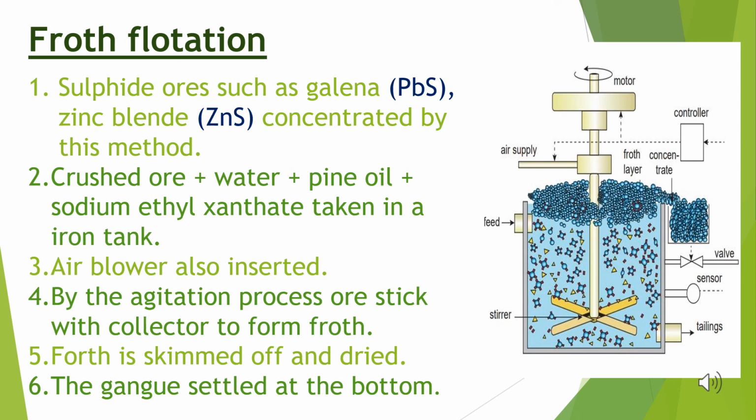The sodium cyanide is used to depress the floating property of zinc sulfide, or to reduce the floating property of zinc sulfide. Here zinc sulfide forms a layer of the zinc complex sodium tetracyanozincate, which is formed as a complex. So we can easily concentrate the galena ore, lead sulfide ore.